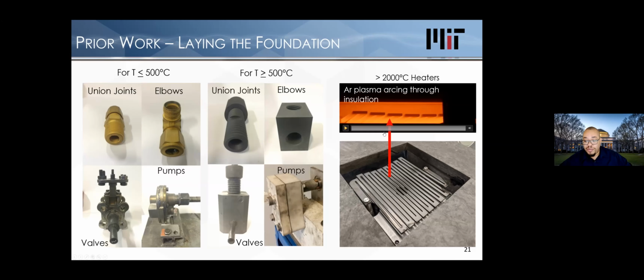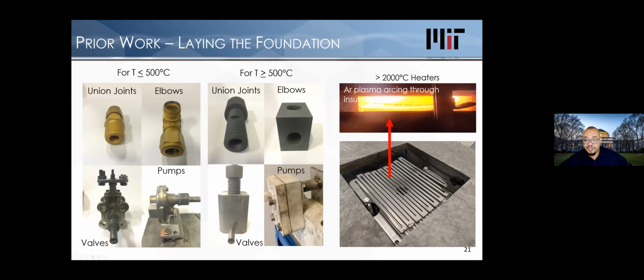This is an interesting problem that happens. This is a heater that we made. We use graphite resistance heaters. One of the interesting things that happens, you get this hot above 2000 C, and everything conducts electricity, including gas. So one of the interesting challenges that we had to solve is even making the heater gets interesting. You got to control and stay at low voltages, which requires high currents. But what's happening here is this heating element from a side view. We cut a hole in the insulation, and the argon actually ignites and forms a plasma. And so what happens here is this is the positive electrode.